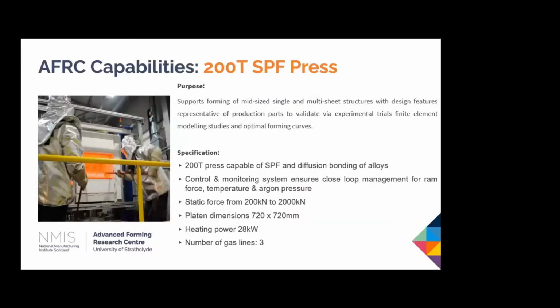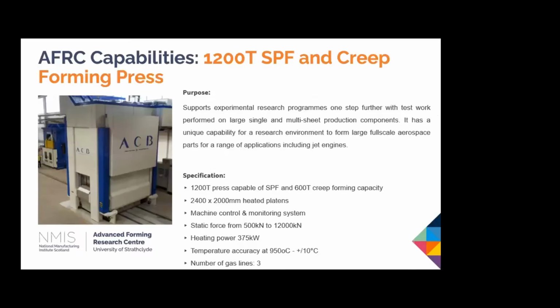We also have, and just going on to sheet metal forming, we have some very impressive superplasticity equipment, for example. So this is a really small one, 200 tons, sorry, just to prove out some technologies. But we also have a 1,200-ton superplasticity press and a creep forming press. So we've proven out creep forming up to 2 or 3 inches thick of titanium in making complex shapes. The other interesting thing about this is that we've got a few independent cooling and heating systems here, so we can locally heat and cool, leading to much more efficient approaches.